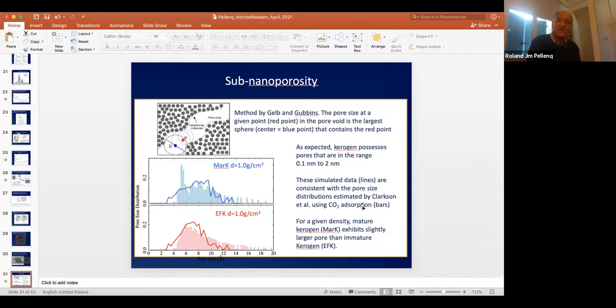So one with lots of oxygen, that will be the Eagleford, the red one, and the blue one is actually the Marcellus, which is very mature, not much high oxygen left. And so this histogram, I don't know which one is which, but yes, the histogram is from simulation, while the curve is from CO2 adsorption measurement. So we can access the pore size distribution by outgassing the sample and putting back some CO2.